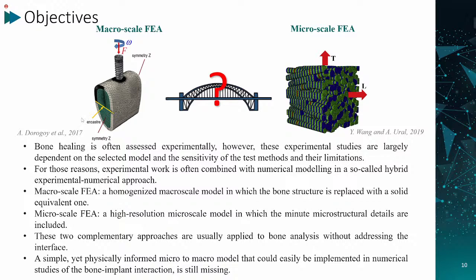There are two often used numerical approaches. First, the macro-scale model. This model is a homogenized macroscopic model in which the bone structure is replaced with a solid equivalent one. On the contrary, the microscale model is a model in which the minute microstructure details are included. These two complementary approaches are usually applied to bone analysis, however, without addressing the interface. So a simple yet physically informed micro-to-macro model that could easily be implemented in numerical study of the bone-implant interaction is still missing. So in our current study, we aim to develop this stochastic spatial and temporal bone-implant interface model.